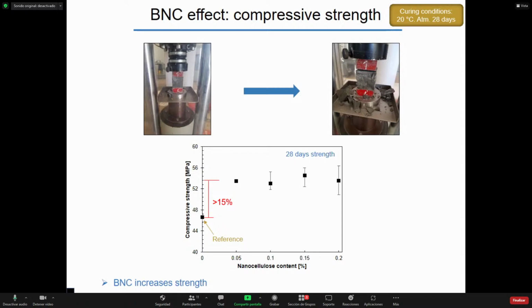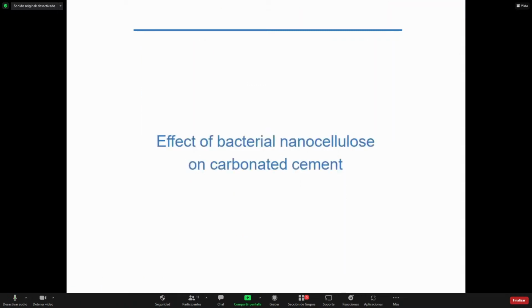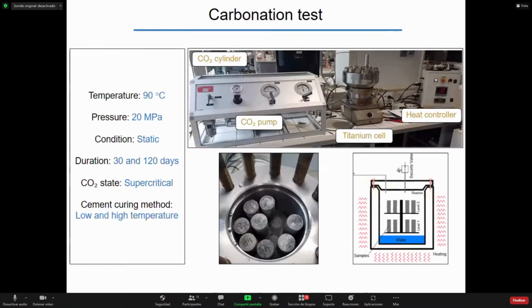Now that we have seen that bacterial nanocellulose modifies the fresh state and hardened state of cement, let's see if it modifies the durability of cement against carbonation. The carbonation test consists of a CO2 cylinder, a CO2 pump, a titanium cell, and a heat controller. We chose a temperature of 90 degrees Celsius and 20 megapascals under static conditions for 30 and 120 days. We used cylindrical samples using both curing methods, low and high temperature.